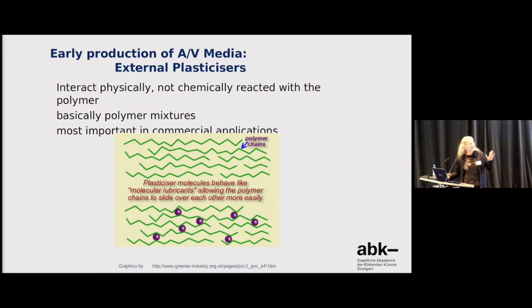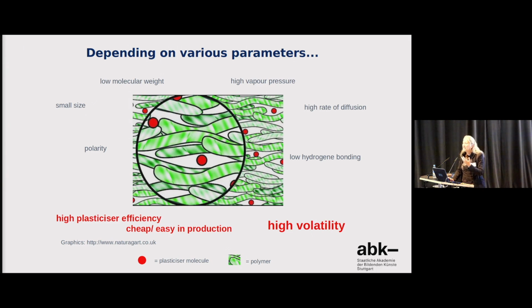So a very tiny look on the production and on the use of external plasticizers. Cellulose acetate has been externally plasticized, which means that this is a mixture. The plasticizer interacts physically, not chemically, with the polymer. It's basically a polymer mixture, and you see these tiny molecules, the round parts here, they help the chains of the comparatively harsh material to get a little bit more flexible. And this is the reason why it can evaporate, because it's not chemically reacted. It's only the molecular bonding inside the material that holds it or not.